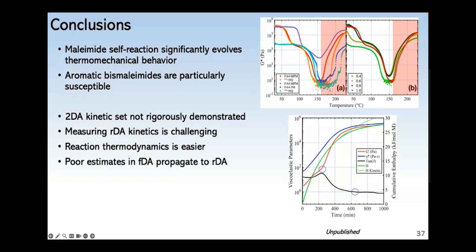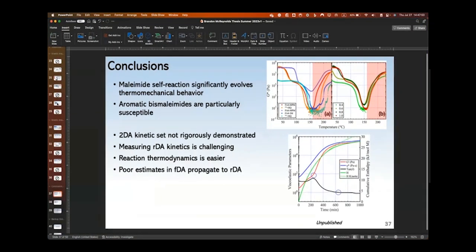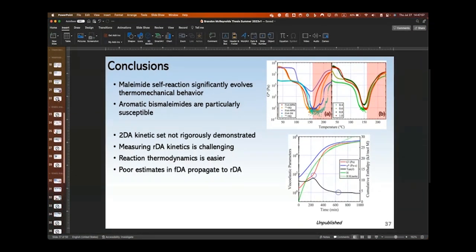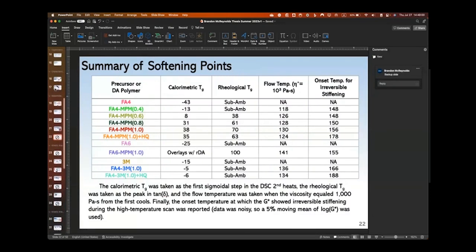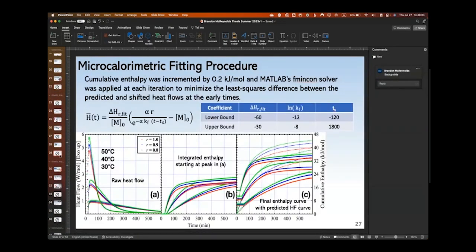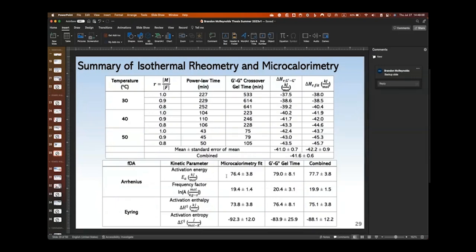Also affirm the activation energy for the forward reactions. So the activation energy that I got from the Arrhenius fitting was about 76. With the Eyring model, about 73. You showed the table comparing those with the literature. Yeah, I have that too.